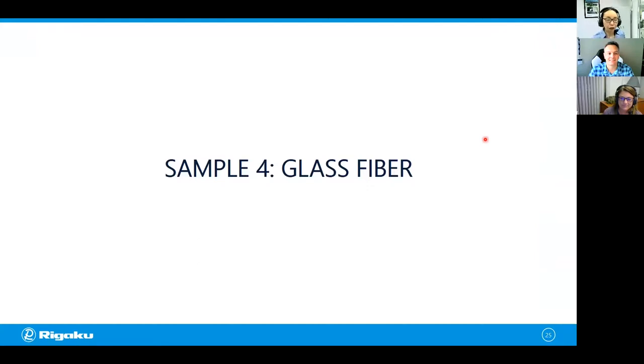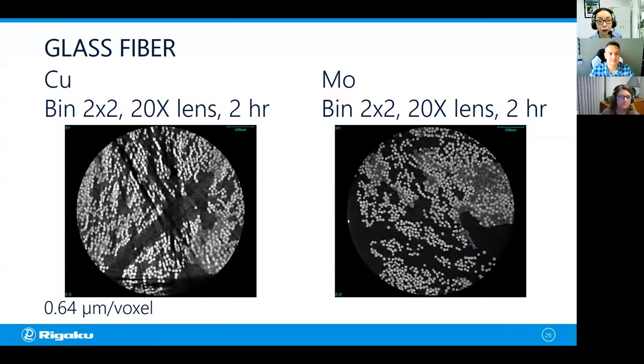Now, for glass fiber scans, it takes about 2 hours at least to see the fibers very well. So I'm not going to make you sit and wait for 2 hours and show you the results. Okay, so those are the CT scans from copper and molybdenum for glass fibers you just saw. When you use copper radiation, this was a binning 2x2, 0.64 microns voxel size scan. It took 2 hours.